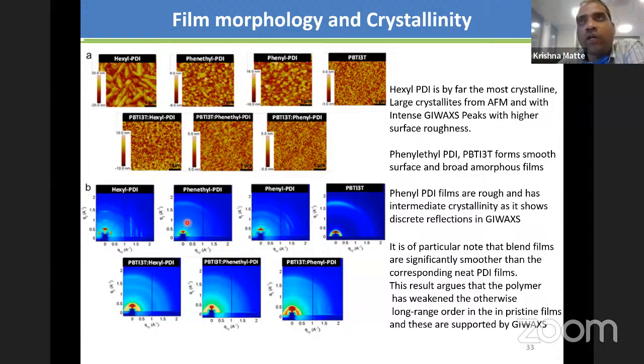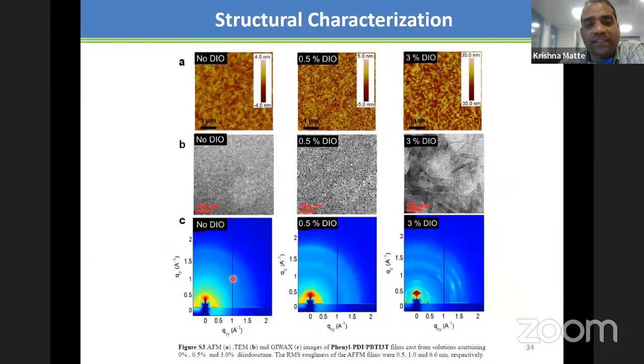What is important for organic solar cells to work is the interface, which means the domains forming between the donor and acceptor, and the crystallinity aspect of it. If you have more crystallinity, it is not good. If you have less crystallinity, it is not good. What we found is that crystallinity intermediate between them is really important for fabricating highly efficient devices. And then we added some additives to control the interface as well as the crystallinity, by adding diiodooctane, which has its impact, and we found that the optimum amount of diiodooctane is critical for having high efficiency devices.